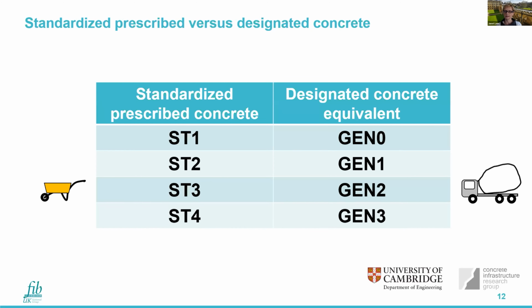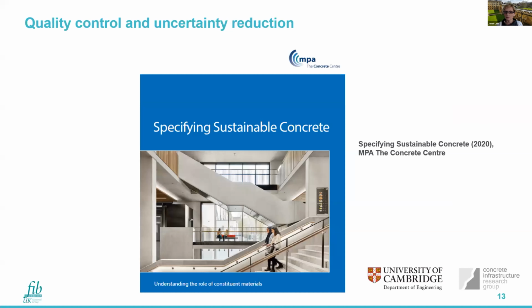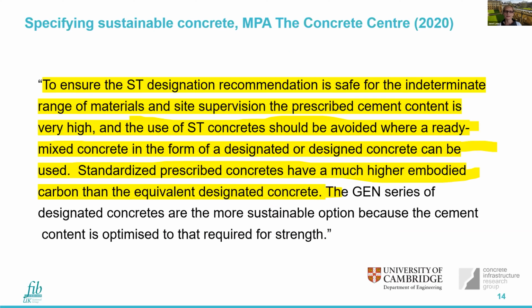Now, this is known and reflected in our guidance. So for example, in terms of the ways to specify concrete, if we look at standardized prescribed concretes, or ST concretes, they accept that these might be small batches, hand mixing, whereas for designated concretes, the equivalent of a ready mix in a GEN class is provided. So these differences are known. And indeed, if we look at the Concrete Centre's Specifying Sustainable Concrete document, if I may read it, it says: to ensure the ST designation recommendation is safe for the indeterminate range of materials and site supervision, the prescribed cement content is very high.